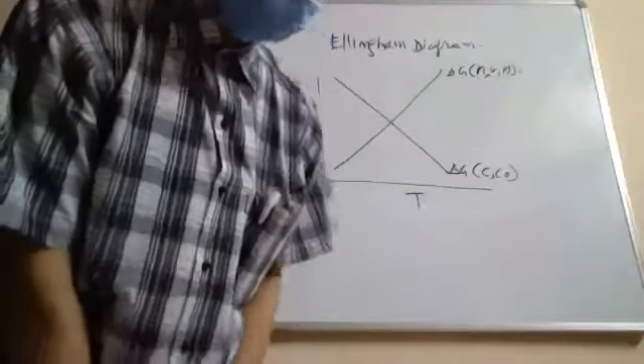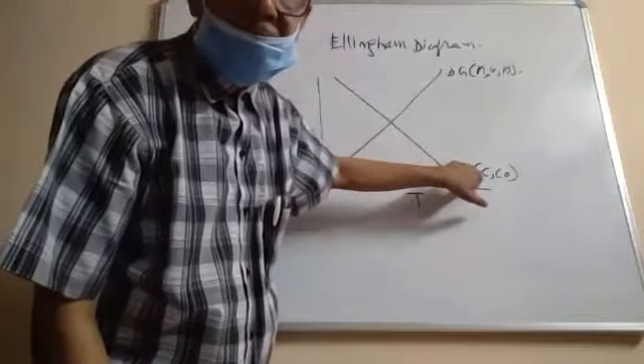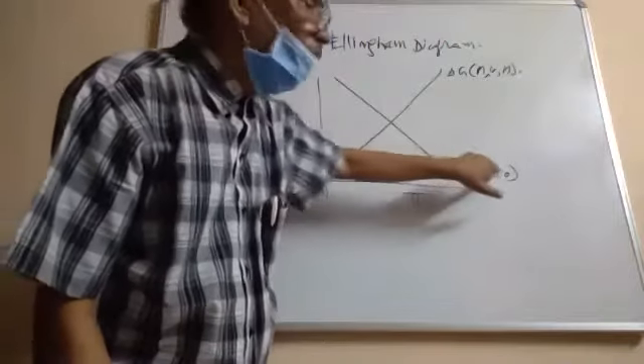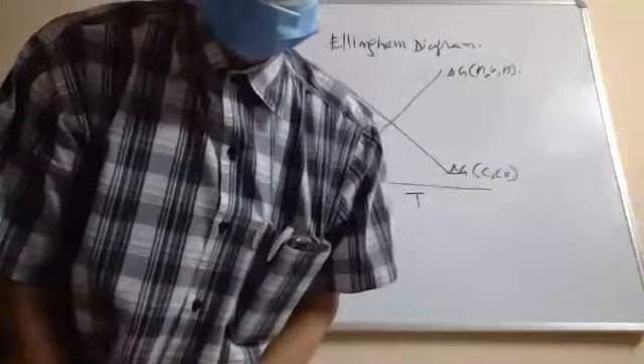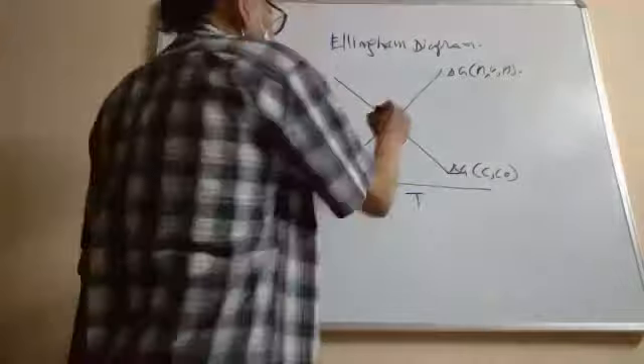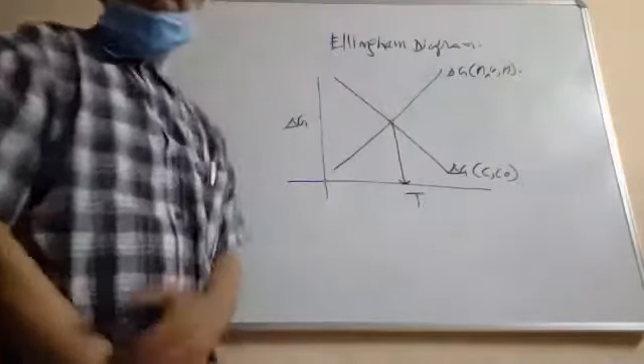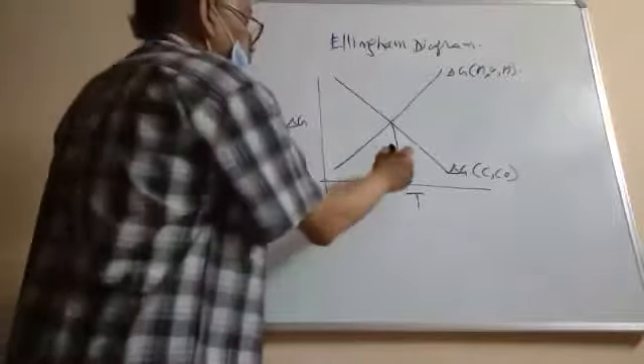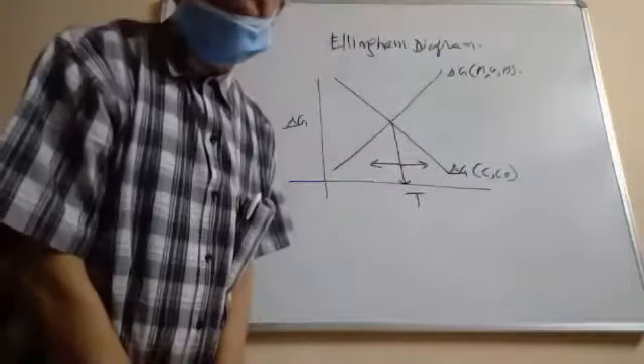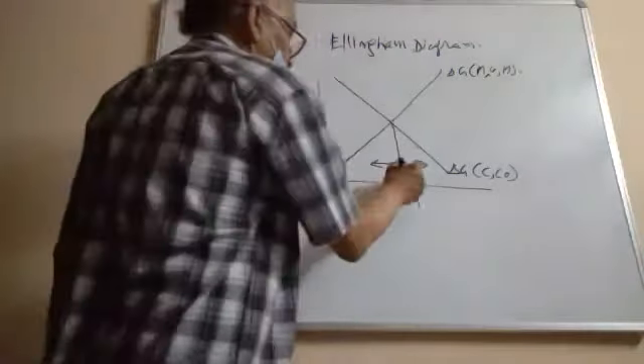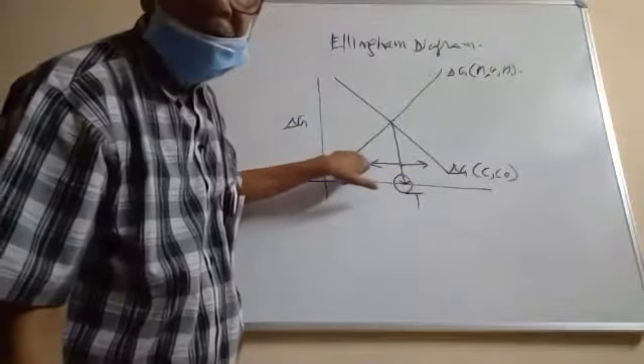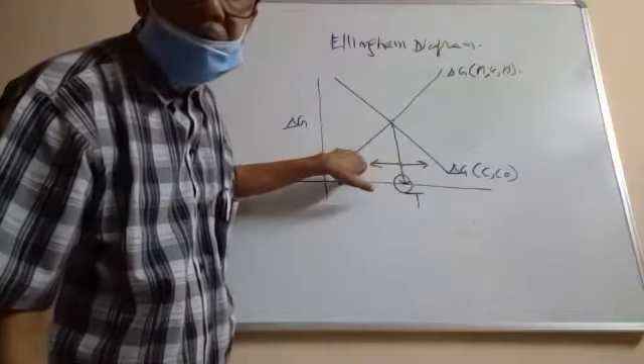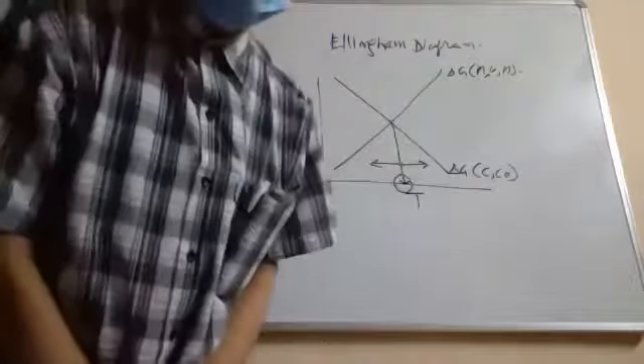Now, here is the trick. If the carbon were to reduce the metal oxide to metal, then the free energy for the formation of carbon monoxide must be more negative than for the oxidation of the metal. Only then carbon can reduce. So this is a critical temperature here, where the lines cross, below which no reduction happens, above which you can see the reduction of the metal oxide by the carbon. So that temperature is the critical temperature. So if you were to treat the carbon with the metal oxide at temperatures below this critical temperature or the crossover temperature, nothing will happen. You won't get any metal.